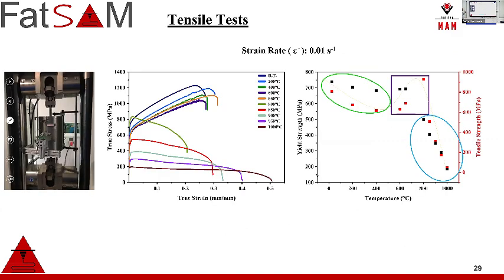during fatigue modeling. Tensile results are quite good, even with increasing temperature there is more than 50% elongation. This is because in our previous 718 projects, we never scanned that much area to obtain a fatigue matrix. We observed that at around 750 and 800 Celsius, a slight microstructural evolution, which we haven't confirmed yet, but probably due to dynamic recrystallization under temperature and loading, and we have an increase in strength and yield of the material, and extremely decreased ductility, even less than at lower temperatures. This is probably strain hardening of the material due to dynamic recrystallization, because the service condition of this material is 650 and we tried up to 1000 Celsius.